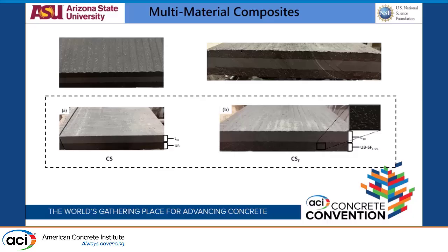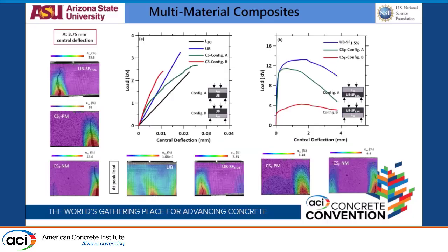cross-sectional prints, but for the sake of being shorter, I'll talk about two sections that we printed. One is with the L30 mix, that's the non-fiber L30 mix, substituting the top half of the beam. Here it's a slab, we'll cut beams out of it, so I'm just going to refer to it as half of a beam. The top half is replaced by L30 and the bottom half is a UHPC mix, and the other has the top half as L30 and the bottom half as a UHPC mix with that 1.5% steel fiber that we saw before. So what happens as a response when compared to this? For the non-fibered ones, we saw near similar peak load performance for the composite sections.